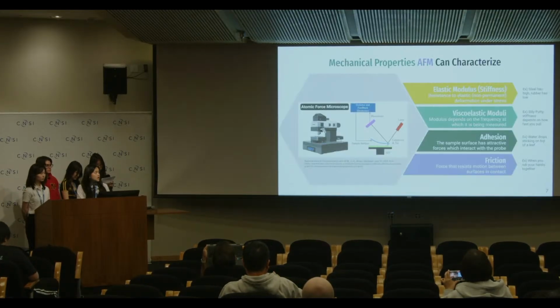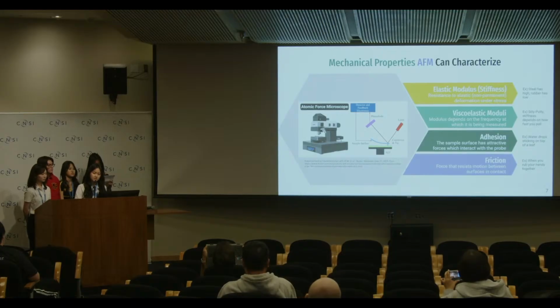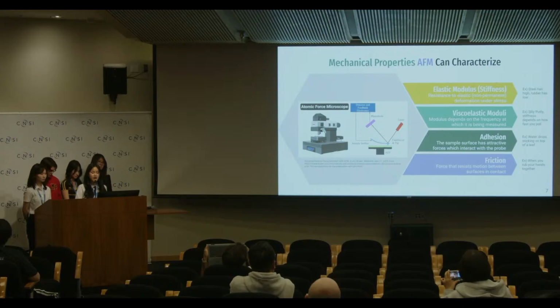Some of these include the elastic modulus, or stiffness, which is also the Young's modulus, as well as viscoelastic moduli, adhesion, and friction. Elastic modulus, or stiffness, refers to the resistance to elastic or non-permanent deformation under stress. An example of this would be steel having a high elastic modulus, while rubber has a low elastic modulus due to how it's easily deformed.